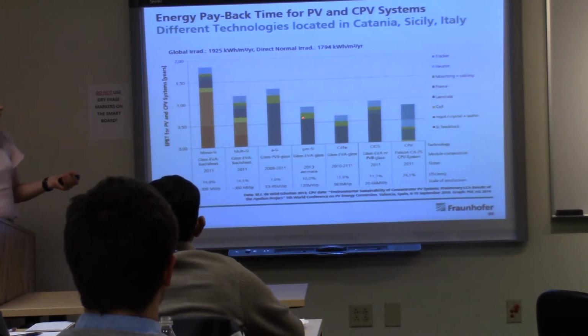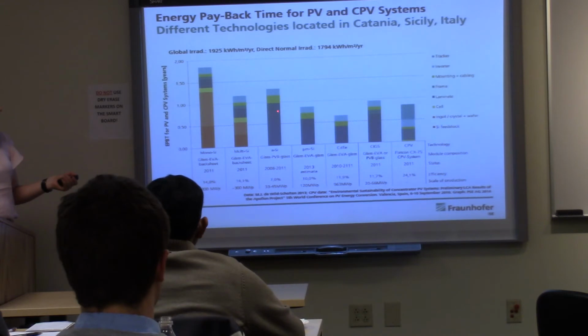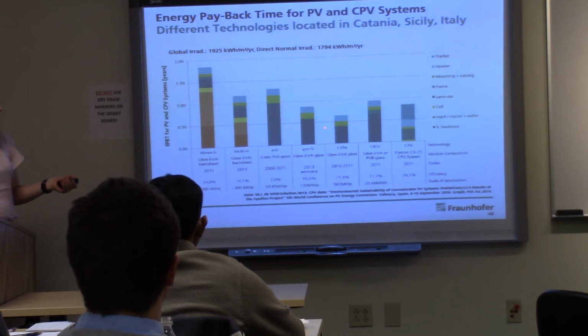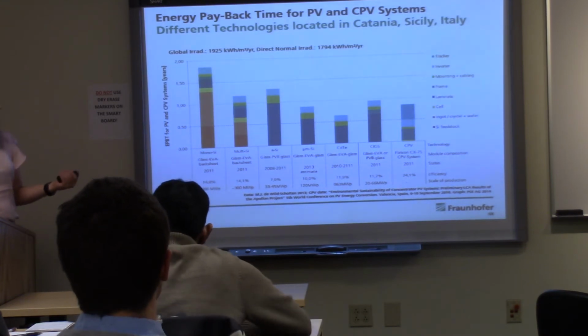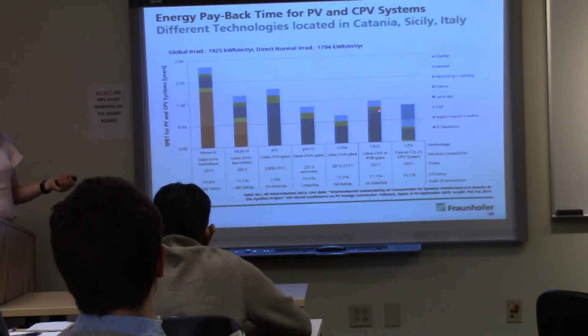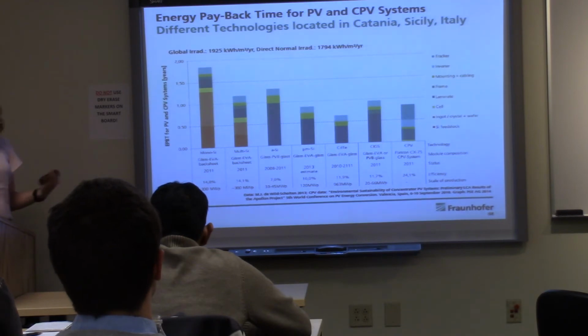Microcrystalline silicon, again, a little bit lower because it's a little less intensive than this and a little more efficient than amorphous. But CdTe, you see here, is pretty low, and most of it's in the other components other than the cell, the CdTe itself. And a lot of that comes from like the glass. It takes a lot of energy to make glass. And then CIGS is a little higher because it's a little more complicated to make, and then finally concentrating PV here. What you can see is CdTe is pretty close to that half a year time, which is where we wanted to get, to generally have a technology that's growing pretty quickly and going to pay back in energy pretty quickly.